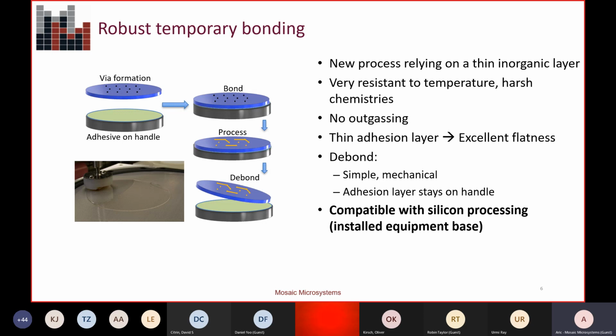But by leveraging our very thin temporary bond, you get very good total thickness variation of the bond, and you don't have to worry about managing flatness. And so you can bond a fused silica wafer and grind and polish it to below 200 microns. We've gone as low as 70 microns, and get very good TTV in flatness using that approach. It's much harder to manage that using a thicker, spin-coated adhesive. So a lot of advantages for using this thin inorganic layer for enabling new technologies in existing processes.